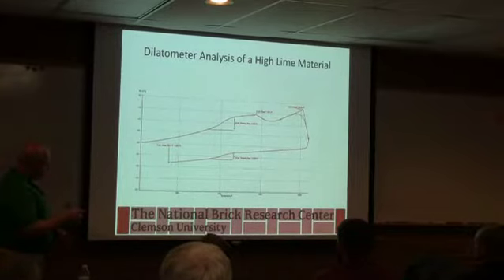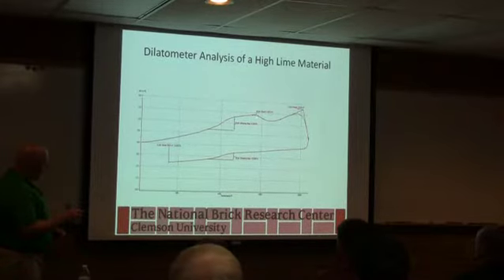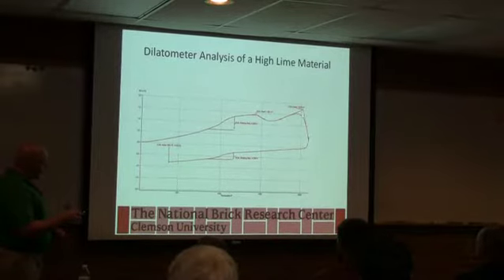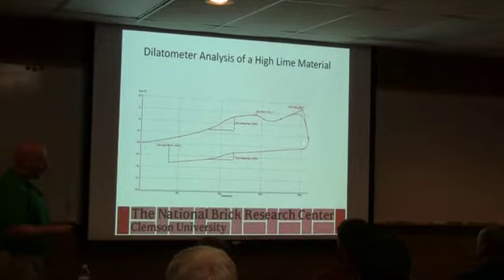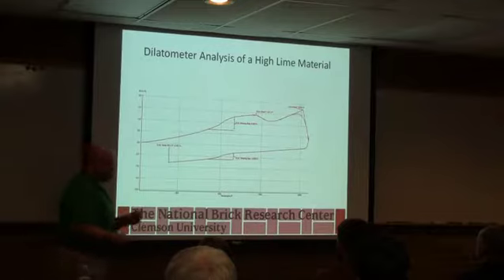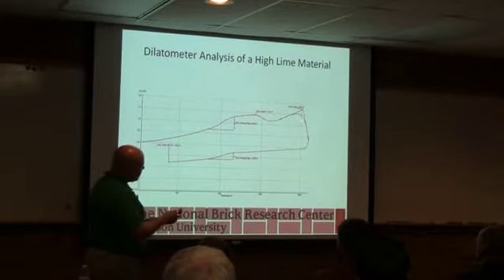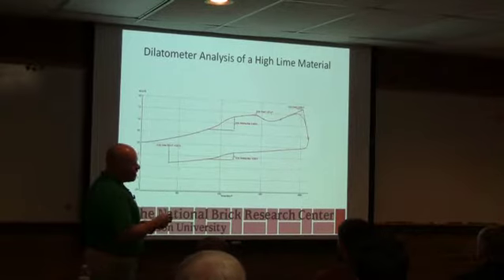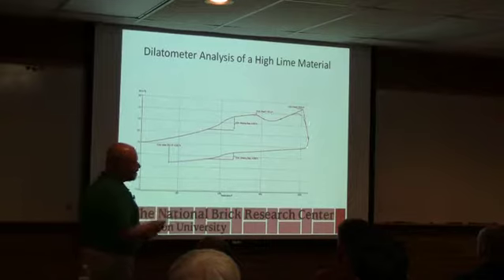But what happens with this material, so we're heating up, this would be the clay mineral decomposing, and then we see the limestone decompose, so you see a shrinkage. And then depending on how much limestone's there and how quickly you're firing, you can make a tremendous amount of liquid in a very short temperature range. So what they normally do is they get up to the point where this almost happens, and they build in a soak, and they let some other reactions take place, and you don't get a puddle.